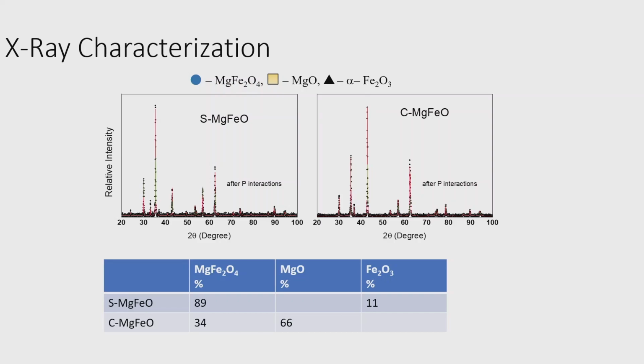And when you put an excess of magnesium, you see that you produce the ferrite, 34%. This was expected by the proportion of magnesium to iron, and 66% of MgO. We are not showing it here because we sent it for publication, but a lot of the MgO is at the surface. So we produced magnesium oxide at the surface of the magnetic material just by putting excess magnesium in the mix.